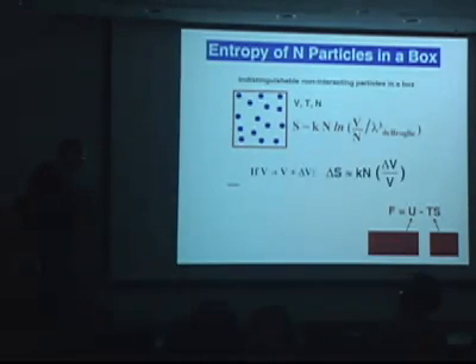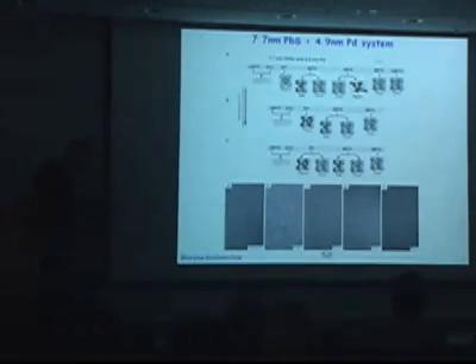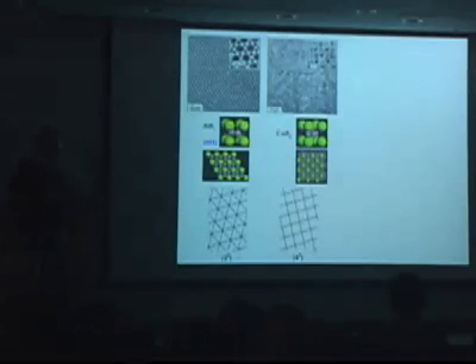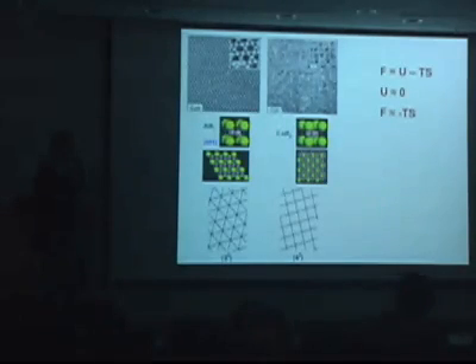So we have a very complex system, and the only way for us to move through this complexity was to develop some nearly empirical rules for how to cancel as many interactions as possible. One of the examples here is that we found how to treat the particle surface in order to end up with electrically neutral particles. So it really minimizes interparticle potentials. Then the free energy will be determined by entropy.